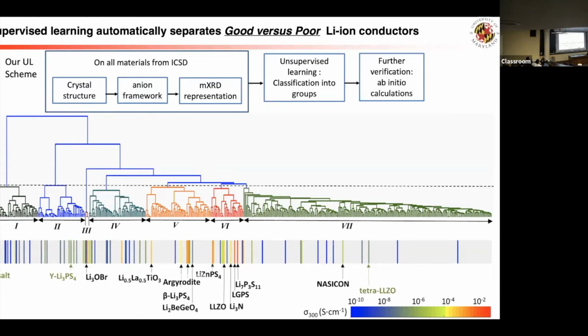Within group 5, we have this perovskite, bromide, beta lithium phosphate, and the lithium, so all that color here. On group 6, you have LGPS, this phosphate carbonate, lithium nitride, and the other phosphate. So that tells you, using this very simple approach, we can indeed find those good materials are similar, which is hard to do by a human, but a simple machine learning algorithm uncovers that.